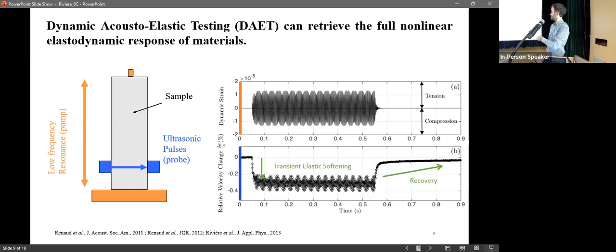And then when we stop the excitation, it recovers, but it takes some time to recover, and it recovers in a logarithmic fashion. Here I'm just plotting 0.3 seconds, but it may take several minutes or several hours to go back to the initial state. So we are in a nonlinear elastic regime, but it's still elastic. In that case, we are not damaging the sample. It recovers, but you need to wait enough time. All the contacts and the micro cracks inside the rock sample have been disturbed, and then they heal over time back to their original state.